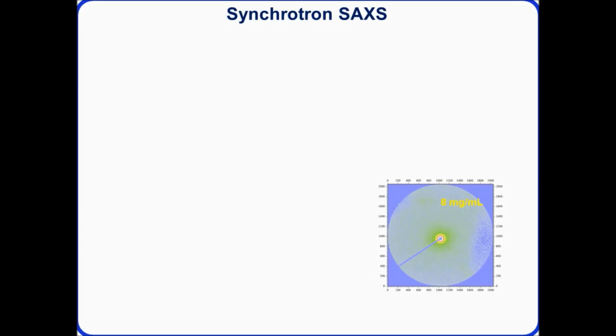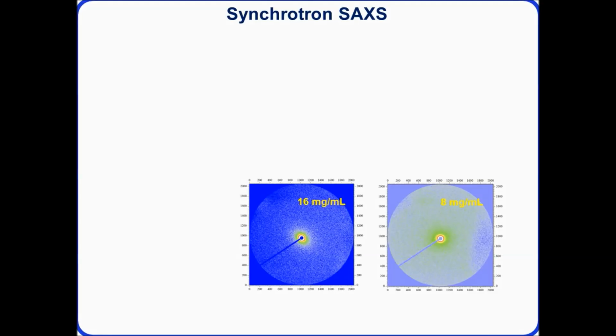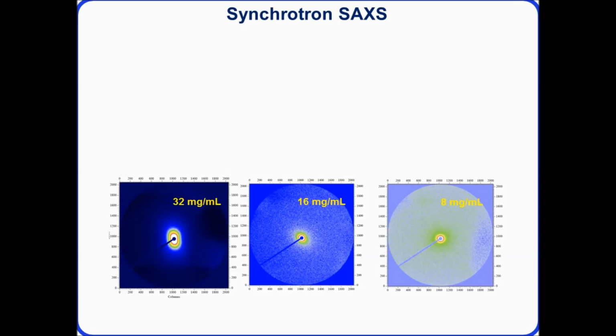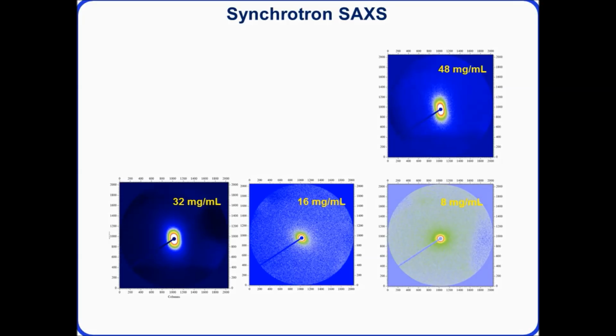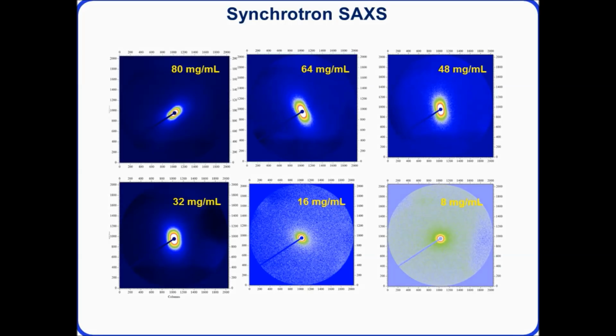If we just look at some data we've performed on a synchrotron, this is called small angle X-ray scattering. I will just show you, as you increase the concentration, so the number here is the loading of the graphene in the ink, you start to see this pattern emerge, which is showing the alignment of the graphene flakes in the solution. As we approach 80 grams per liter, and we can go even further than that with the microfluidic process, we can go up to 100 grams per liter, we have a huge amount of orientation and preferential alignment of these liquid crystals.